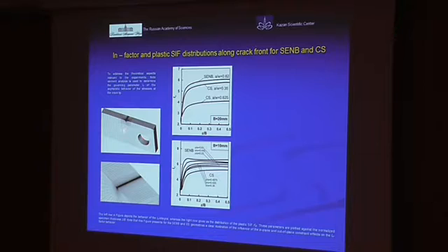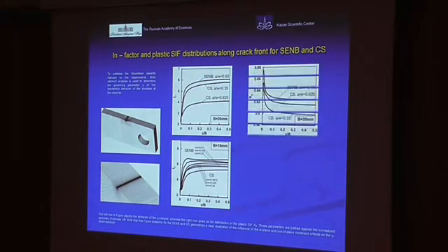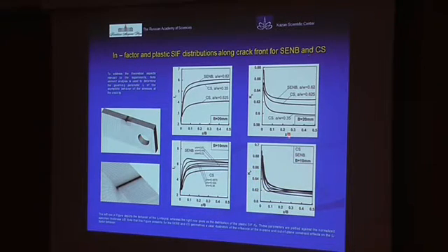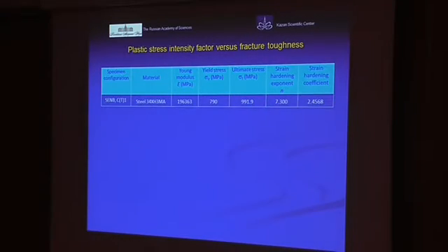Some experimental results. First of all, I would like to show you the behavior of the governing parameter, the In factor, along a crack front, for instance for compact specimens, from the free surface to the middle section of the specimens. You see that this governing parameter is a function of specimen geometry and dimensionless crack length. The next figure shows the variation of the elastic stress intensity factor from the free surface to the middle section of tested specimens.